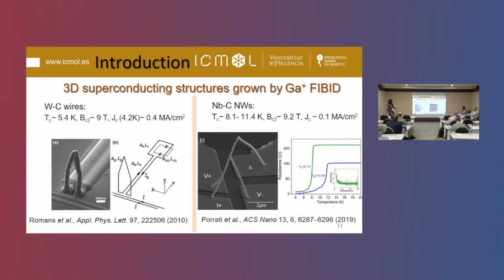So in this case, we can find just two examples of 3D superconducting nanostructures grown using Ga+ FIB. The first one was reported in 2010, some time ago, tungsten carbon wires, but as you can see in the SEM image, the resolution is pretty poor. I mean, the diameter of the wire is around 250 nanometers. Although the superconducting properties of these materials are comparable to the superconducting properties observed in planar structures.